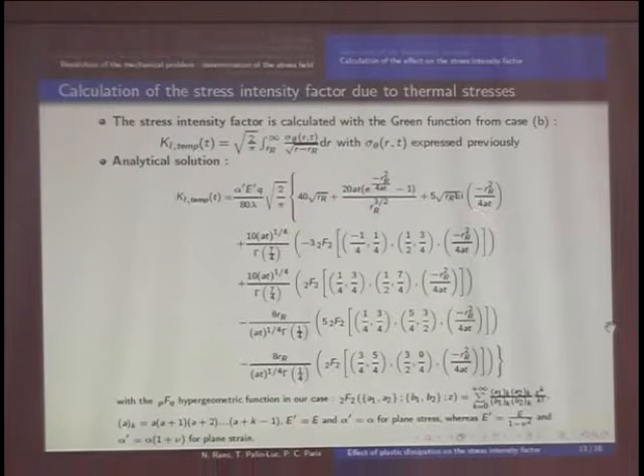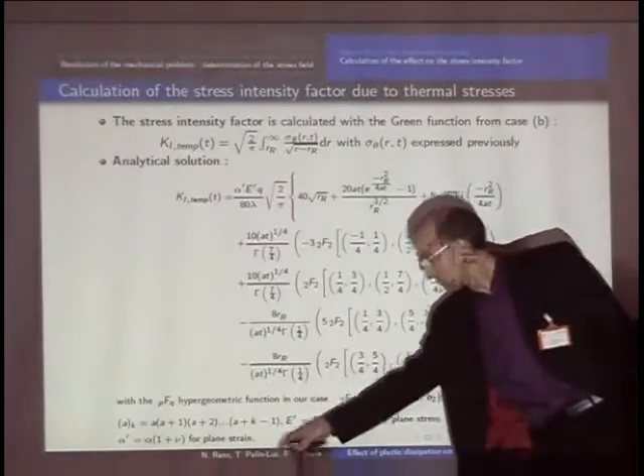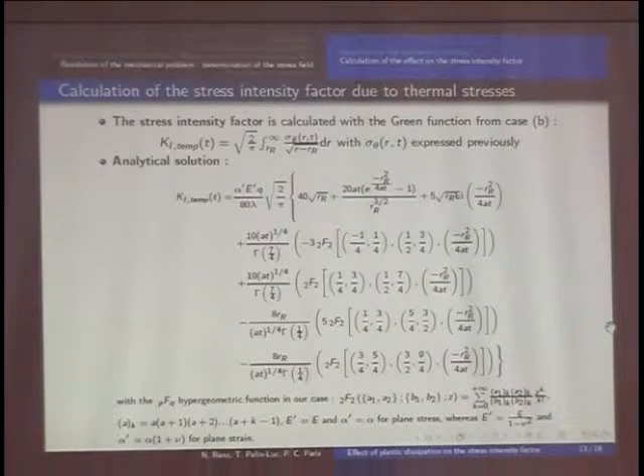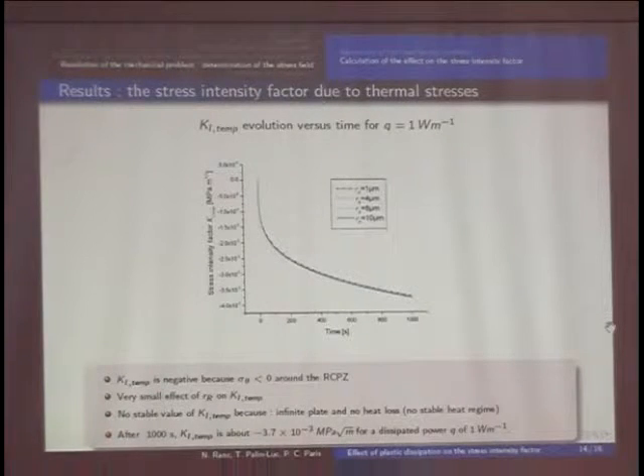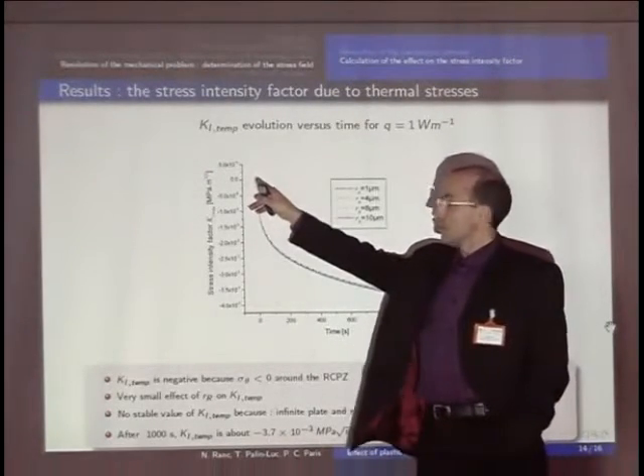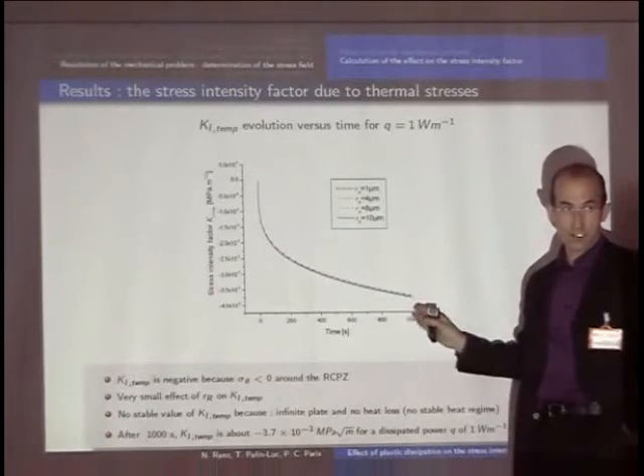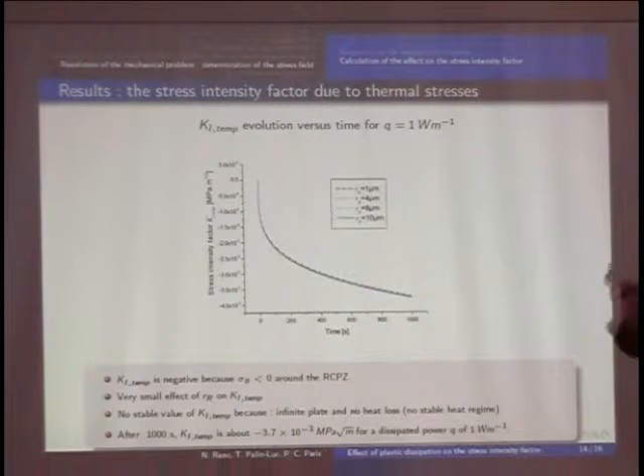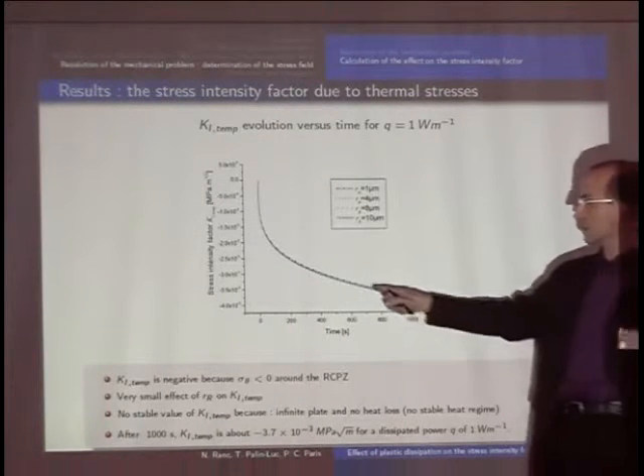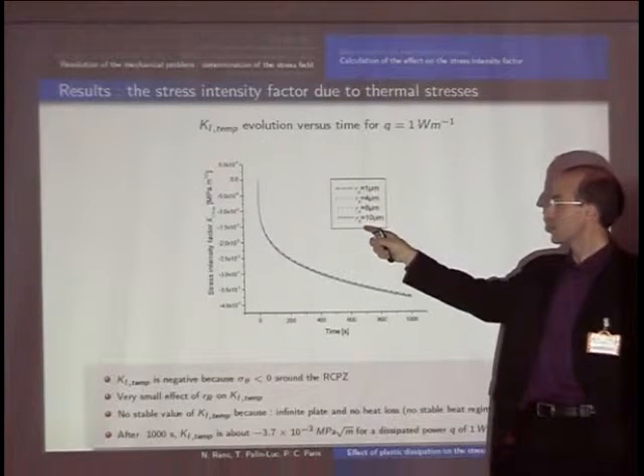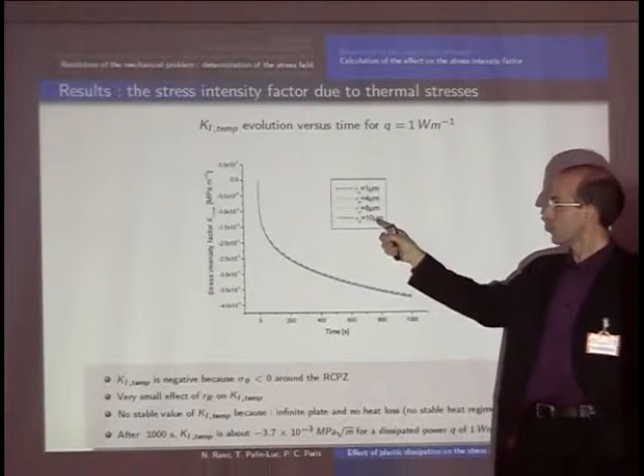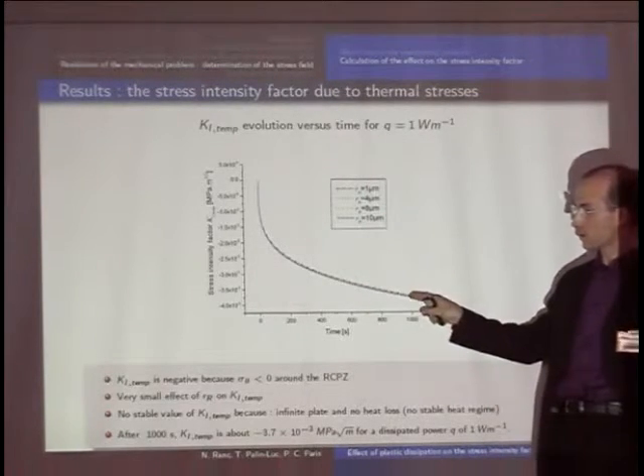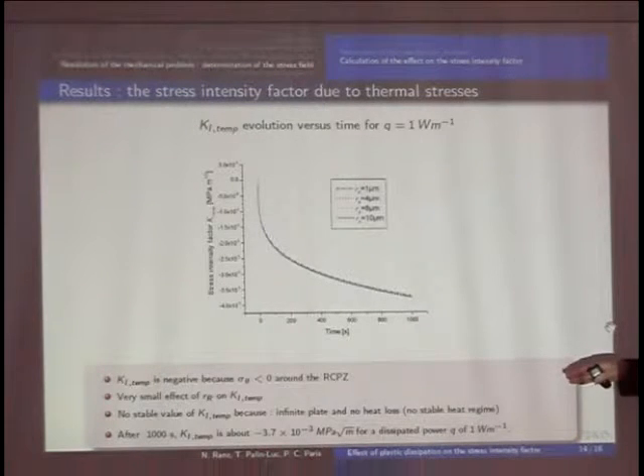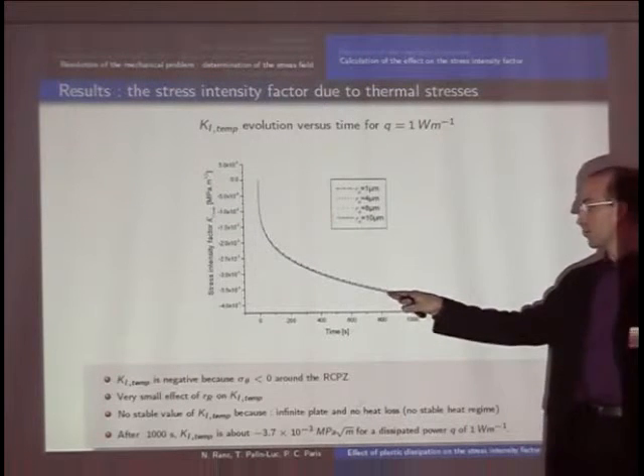This equation is also interesting because it has been solved in two cases, in plane stress and in plane strain. So it's interesting for estimating what happens in the two cases. If we plot this versus time, we can see the following curve. The stress intensity factor due to temperature effect is negative. It's negative because in fact there are compressive thermal stresses. It's interesting also to note that if we compare the different sizes of the reverse cyclic plastic zone, one order of magnitude here between the two curves, the difference is very, very small. It can be negligible.